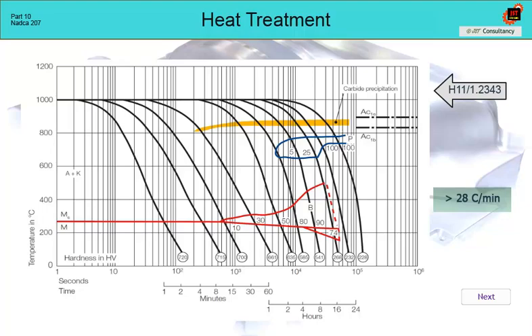Over time, new steel materials have been developed that have this parameter much more freely. It is primarily Dievar from Uddeholm, partly HP1 or TQ1 from Kind and Company. On this CCT diagram, we see the critical hardening points for H11 steel. The cooling rate is close to the limit of carbide precipitation and already partially penetrates the bainite.